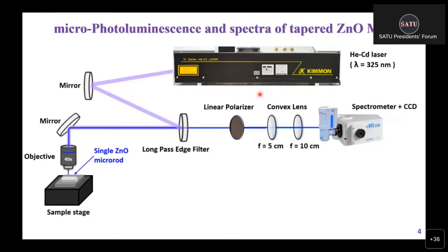And this is the micro-PL setup. We use a helium-cadmium laser for the excitation, which is a CW laser. We use the laser to excite a single ZnO microrod on the stage, collect the emission from the objective, and conduct it to the spectrometer behind. The polarizer used here is to distinguish the emission of different polarizations. We define TE polarization in this direction, which is perpendicular to the long axis of the rod, and TM polarization in the direction parallel to the long axis of the rod.